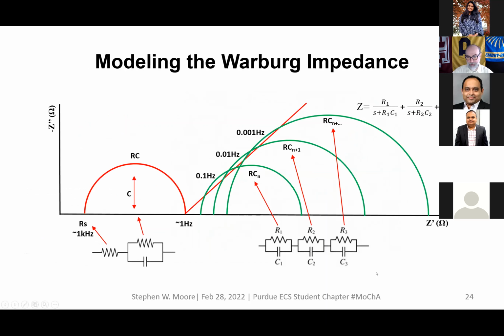You have to do something like this. And I will explain this quickly: you use a series of RC networks, and you maybe use RC network 1, and you draw the little semicircle, which approximates the Warburg impedance. Then you use RC2, and you draw another semicircle, which approximates the Warburg impedance. Then you do RC network 3, and you draw another semicircle, which approximates the Warburg impedance. And you just keep on drawing these circles, and you see that the green line mostly approximates the red line. And you can crawl up the Warburg impedance by just keeping on adding these things on.